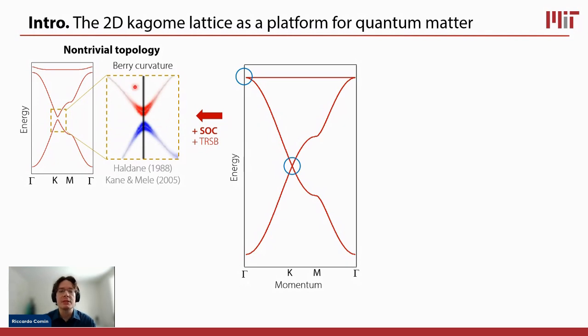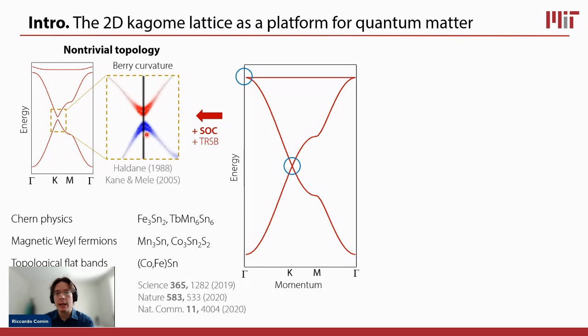And so this monopole of Berry curvature, what it will do is it will activate various different kinds of topological effects that have been seen in a variety of these Kagome-based materials. So we have Chern physics, where we have essentially something that behaves closely to a quantum anomalous Hall insulator. We have magnetic Weyl fermions, and we have these topological flat bands as well. So these topological effects essentially arise from breaking the degeneracies in this band structure. So where we have bands that are touching each other, if we can break the degeneracy at the band touching points, then we can potentially activate these topological effects.